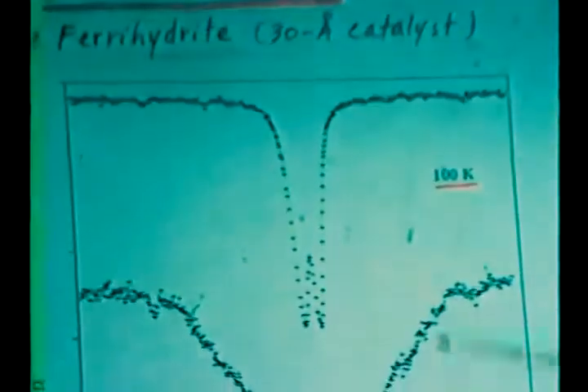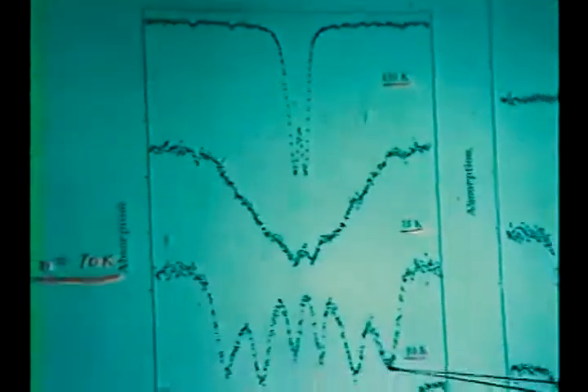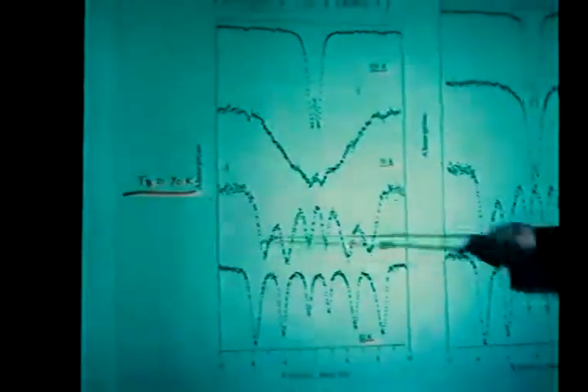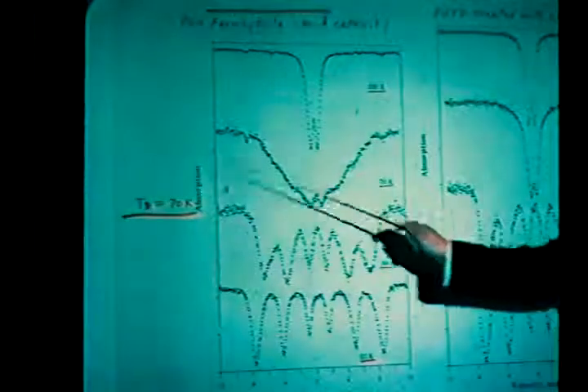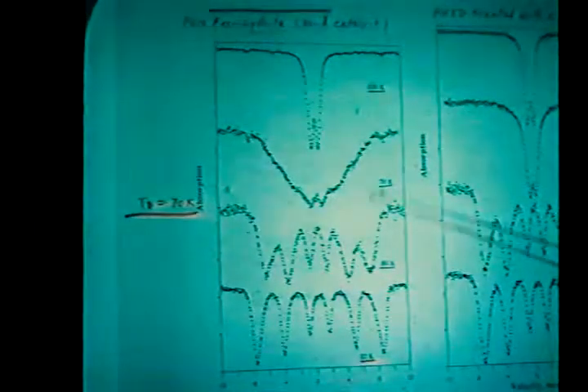Fortunately, we have both. We have 30 angstrom particles, and we have catalyst sites at the surface. Here I'd like to show you first, this is pure ferrihydrite, the 30 angstrom catalyst. At the blocking temperature, around 75 K, you see a complex spectrum, and below 75 you see 6 lines. So we say the blocking temperature is about 70 K.